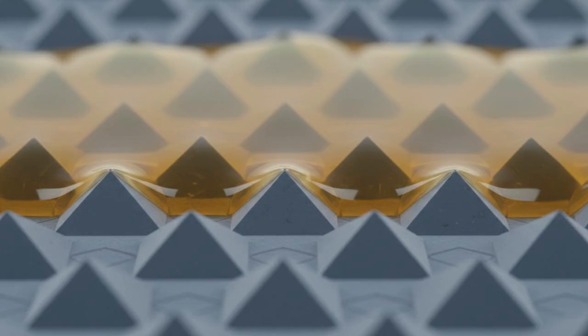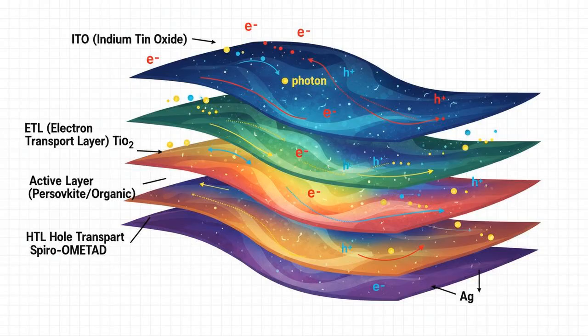To solve this, researchers utilized incredibly advanced deposition techniques. For instance, a joint effort by the King Abdullah University of Science and Technology and the Fraunhofer Institute for Solar Energy Systems unlocked record-breaking efficiencies on textured silicon by using specific molecules like 1,3-diaminopropane dihydroiodide to passivate the uneven perovskite surface. This chemical treatment healed the microscopic defects at the interface, significantly reducing electron-hole recombination and increasing the open circuit voltage to over 2.01 volts.